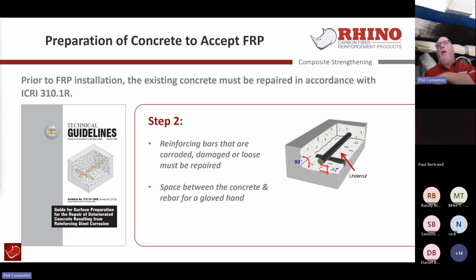So you have to treat the bar, get down to the rebar, but make sure of what I call a finger space. When you're exposing rebar in a full depth or partial depth repair, it's important to be able to get your finger around that bar you're trying to reinforce, I don't care the size of your finger. If the rebar is that corroded, get rid of it. Cut back to the point where you can find good bar, cut that piece of bar out, put a coupler on and add a new bar, okay?